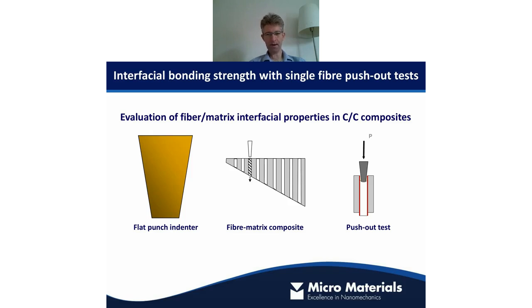And we have tested this, or our customers have tested this, by using, instead of sharp indenters, in this case flat punch indenters, typically with a flat end of around 5 or 10 microns. They take specially thin samples, and they accurately use the nanotest to target the middle of one of these fibers, and then they push it down. As they push, at some point, as the friction is overcome and the strength of the bonding is overcome, the fiber is essentially pushed out into the material. And if you look at the back side, you can see the fiber sitting up.